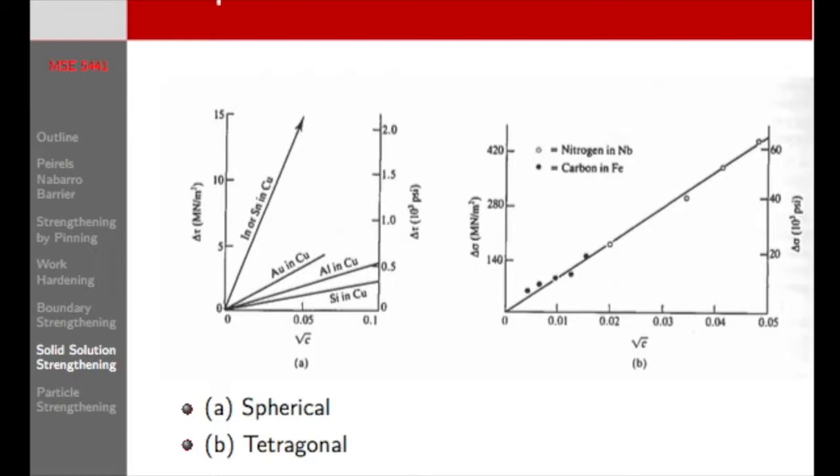This is the change in the stress and the yield stress, right? So 140 MPa with a relatively small amount of carbon addition, right? If you keep extending that out, you look at the effect of nitrogen in niobium, it's huge. You'll never be able to get those kind of strengthening effects from a purely substitutional alloying.